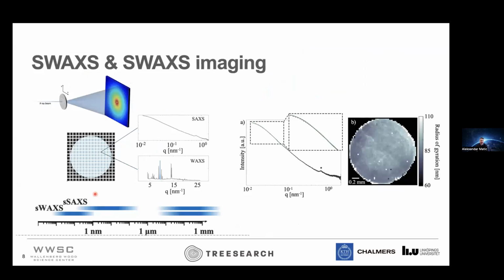So if we start with the small and wide angle X-ray scattering imaging, what you basically do is, if this is your sample, you just raster scan over the surface of your sample and take a full small and wide angle X-ray scattering pattern in each pixel, and then you select a special region. You can say, I'm interested in imaging this peak, which maybe is of interest regarding crystallinity. Or in this case, we were interested in the aggregation phenomena, looked at in the low Q region here in the SAXS pattern. And then we image this over a full sample, which you see here is something like 1.5 millimeters wide.